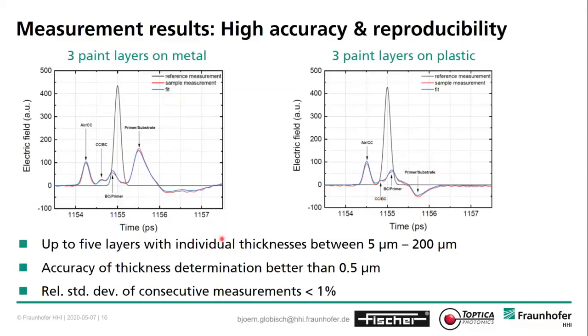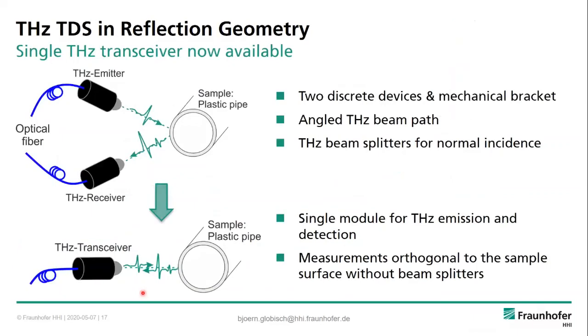And what we get with this system is we can measure up to 5 layers with individual thicknesses between 5 and 200 microns. The accuracy of this is better than 500 nanometers, actually. And the relative standard deviation of consecutive measurements is less than 1%. So we have a quite accurate and reproducible measurement system. And the next thing that we are actually quite...